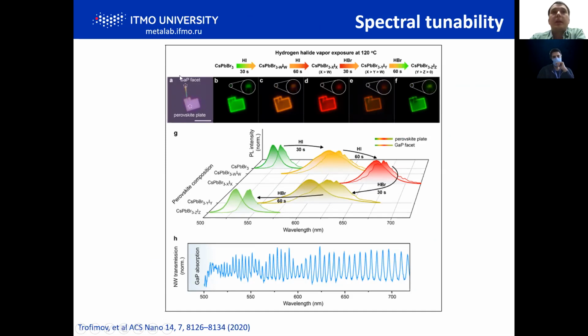So we created this micro laser with a nanowire, and then provided this anion exchange reaction. By applying hydroiodic acid, we shift the photoluminescence to the red region and then shift it back. Of course, there are some defects, but still we demonstrate that it is possible to tune this integrated system just after fabrication.